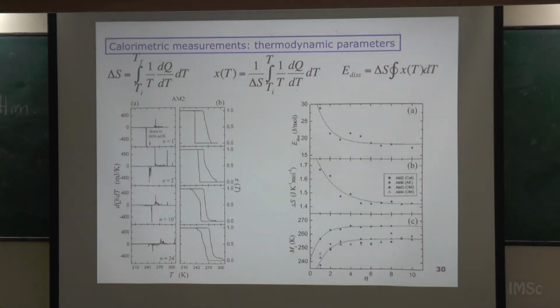Associated to this cycling, you can also measure, for instance, calorimetry. This is one advantage in first order phase transitions. When you cross a first order transition, you have latent heat. So you can put a calorimeter that, if it has a good temporal resolution, you can see how the transition is advancing, because every time there is a new phase advancing, there is heat release. Of course, the resolution you have with a calorimeter has nothing to do with the resolution you have with acoustic emission, because in acoustic emission, you reach below the microsecond scale, okay?